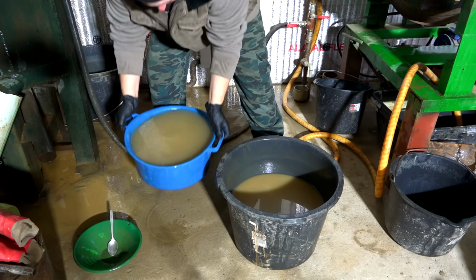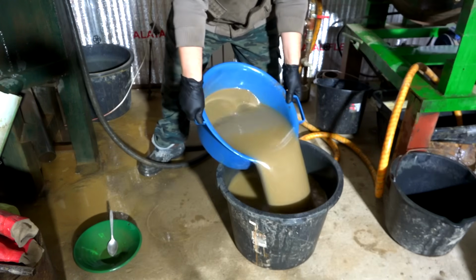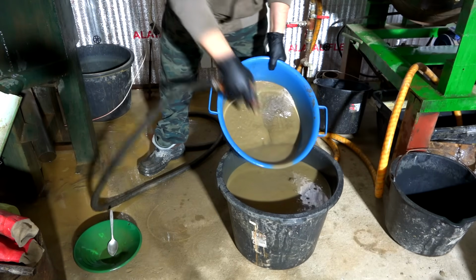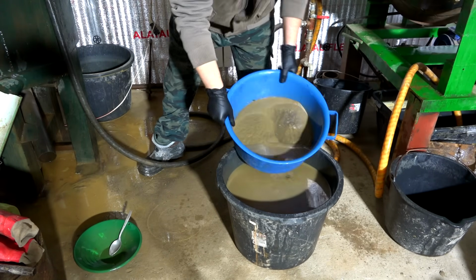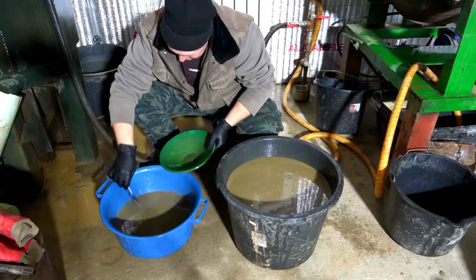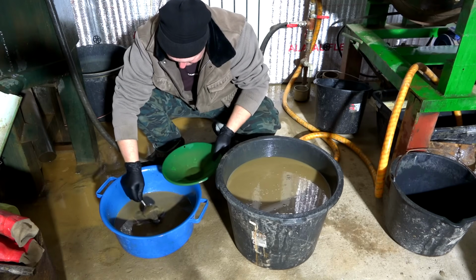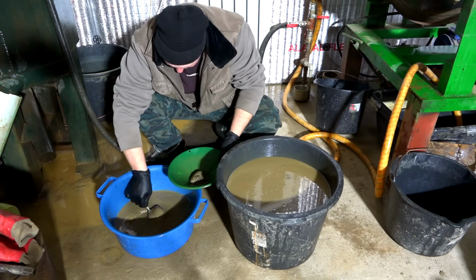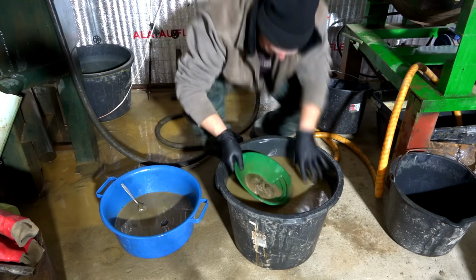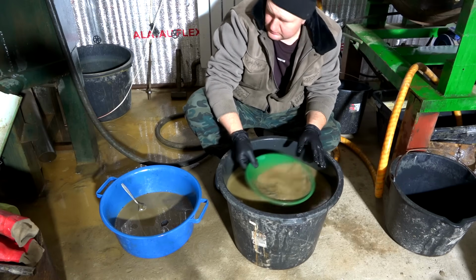After enrichment, I take a sample, take a small amount of concentrate, and wash it with a prospector's pan. If there's no visible gold, I further process this concentrate using various methods. There are many, including flotation, alkaline leaching, and pyrometallurgy.